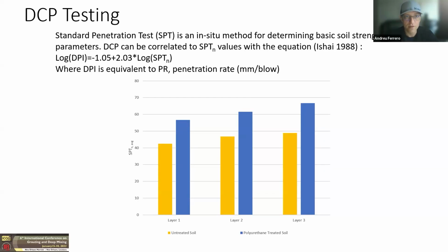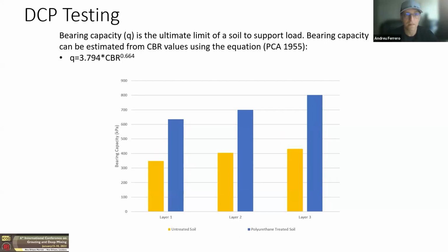Same thing for the SPTN average values. I used a correlation from Ishai in 1988 to correlate the penetration resistance values, or the DPI values, to SPTN values. And here again, we see a significant increase in the SPTN value for the polyurethane treated soil over the untreated soil.